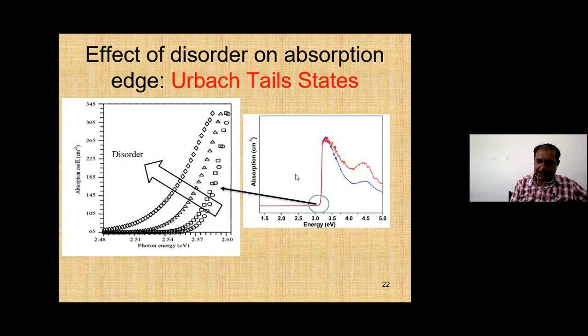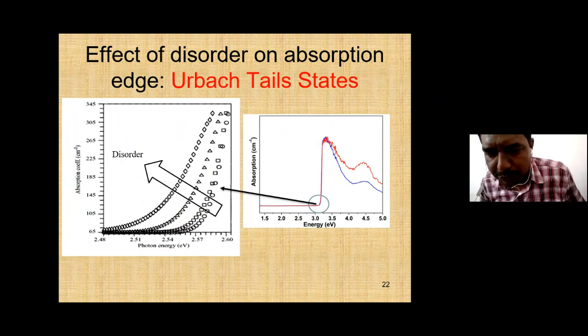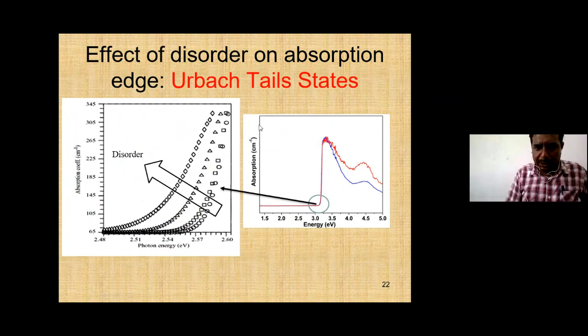This is a simple reflectivity experiment, in which the reflectivity spectra is converted into the absorption spectra using the Kubelka-Munk model, or Tauc plot, you can say. Then you analyze the tail part of this optical absorption spectra and see how the optical absorption is falling down. From the quantitative analysis of the e raised to minus alpha type of behavior, you can quantitatively determine the disorder present in the sample.